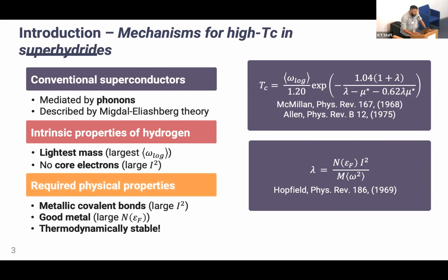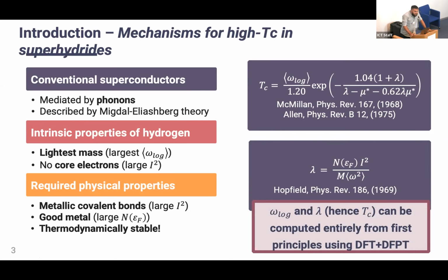Of course, this is not enough to give us a high TC superconductor. The other ingredient that we need is, again, to maximize the electron-phonon coupling lambda. So we need to maximize this matrix element here. And we have learned from experience that this is boosted in directional covalent bonds. Now, usually in nature, these are found in insulators. But for a superconductor, we need to have a metal. So we also need to maximize the density of states at the Fermi level. And finally, we need, of course, a material that is thermodynamically stable because we want to be able to make it in the real world. Now, all these quantities are accessible by density functional theory and its extensions.